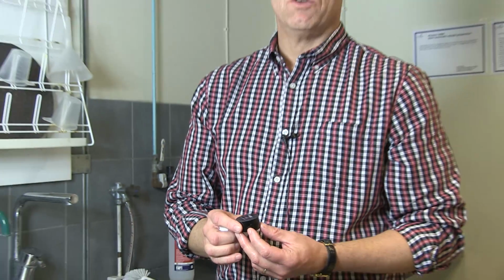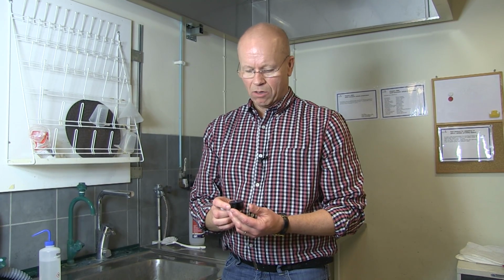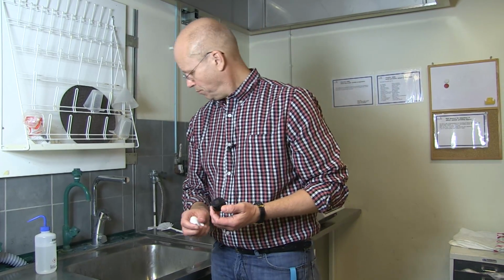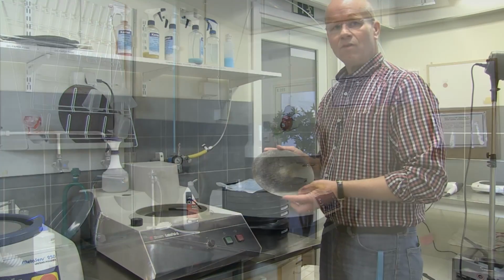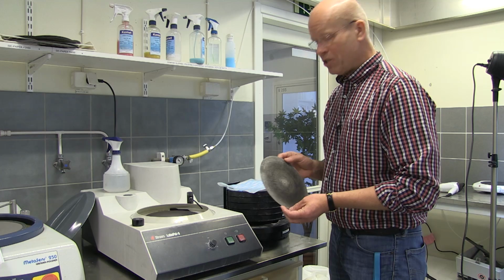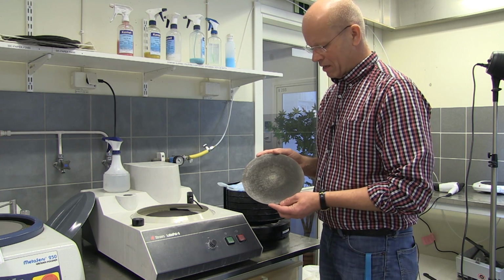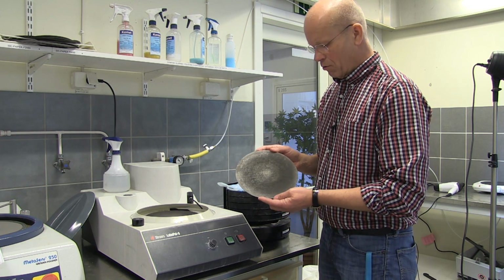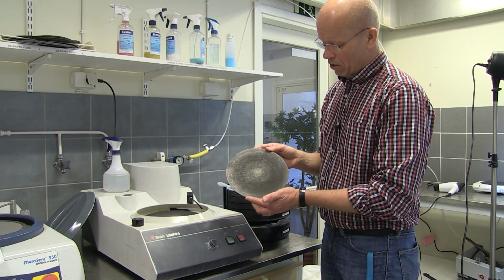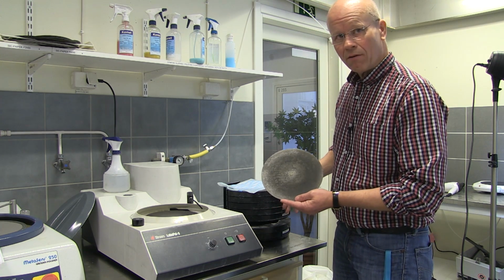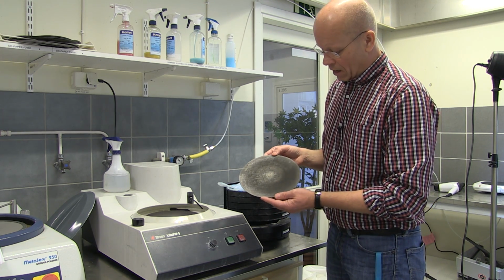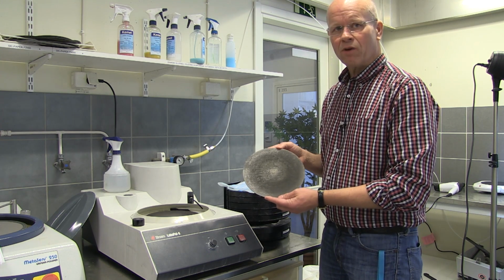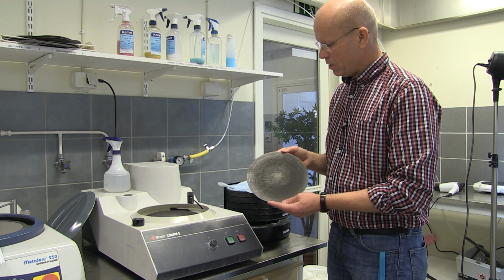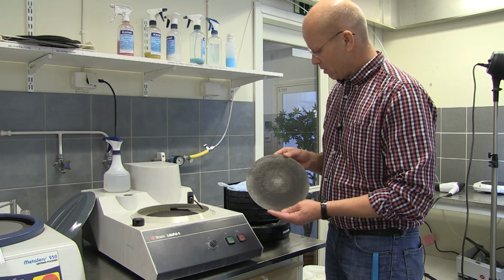So now I will continue to polish on 3 micron diamond and finish with what I call final polishing. So please follow. So after finishing the 9 micron step, cleaning the sample properly, I move on to the 3 micron step. And I can find a cloth in this cabinet, again, marked 3 micron. And as a matter of fact, I will not demonstrate this. I have already done it, but just to let you know, this is the 3 micron one.